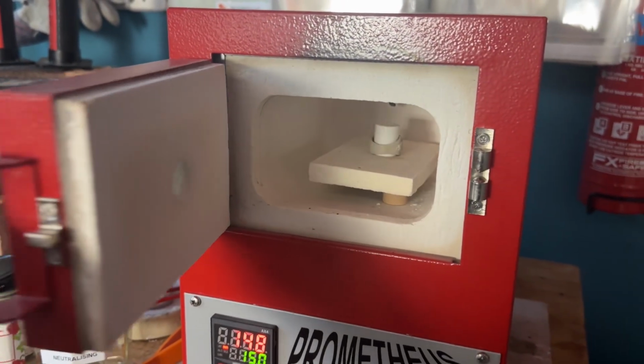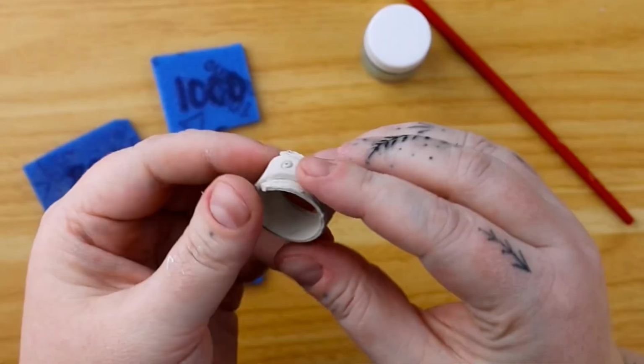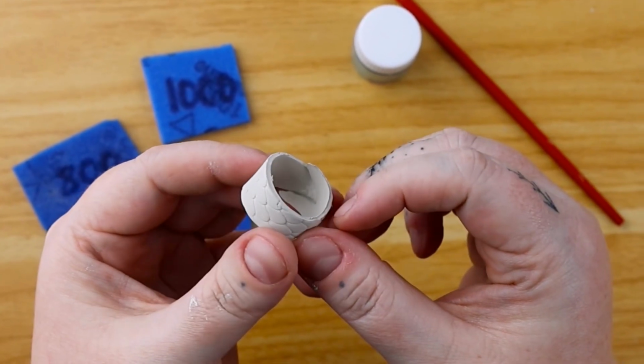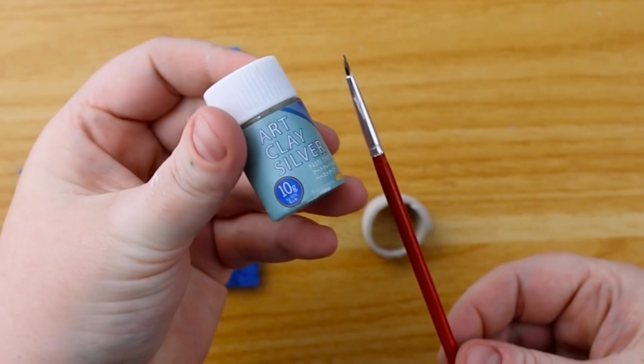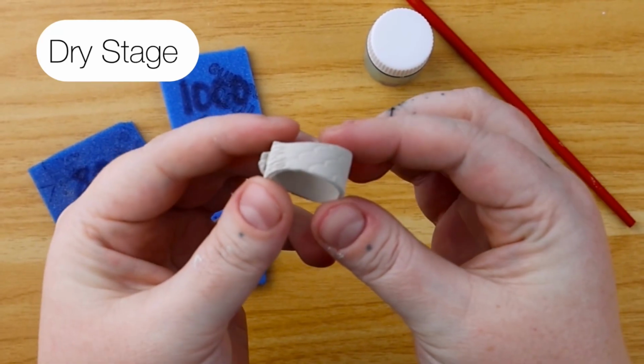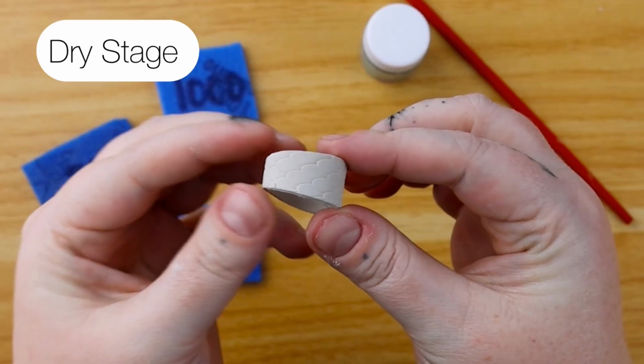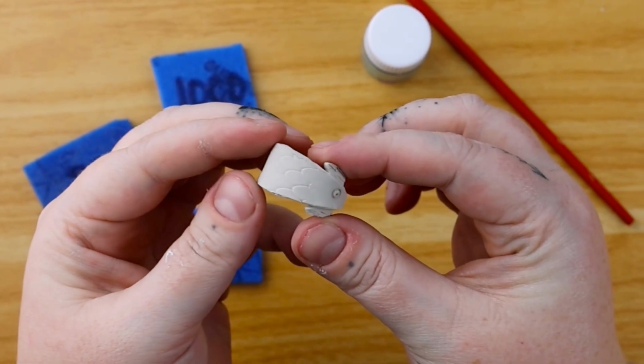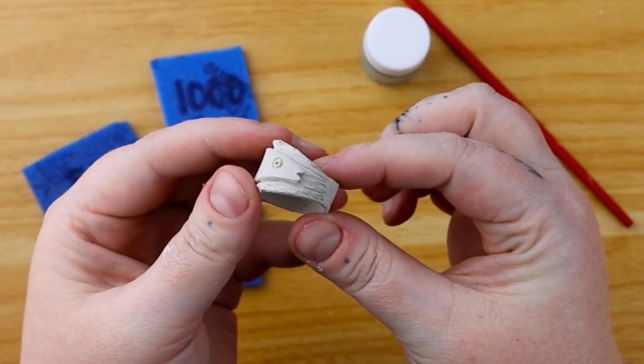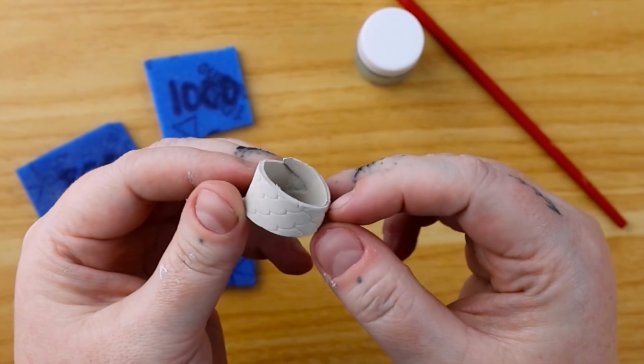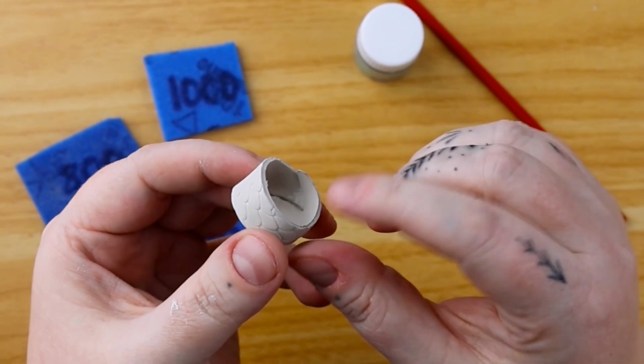Once your piece is fully dried, you can pop it off your mould and remove the paper. After your piece is dry, come back in with some silver clay paste and check for any fine cracks. This can appear because the clay shrinks as it dries, so this stage is your opportunity to refine and perfect everything before firing. Here I'm showing you the edges and pointing out exactly where I'm filling.